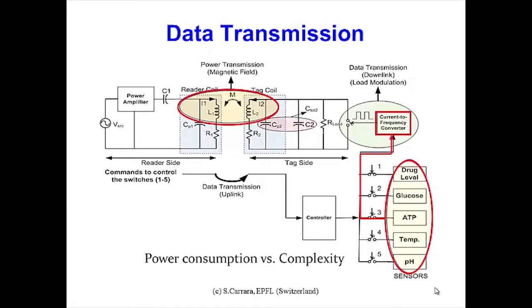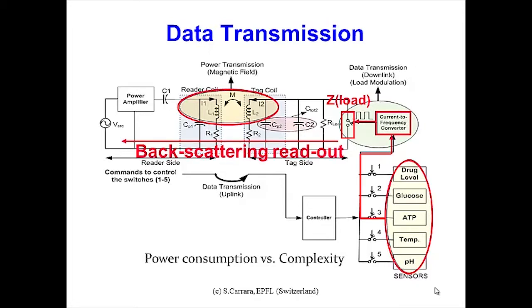transmission is very efficient if we have an impedance matching between the first and the second network in the system. If we are out of the best-match impedance condition, we are able to measure here this bad coupling between the first and the second network. So we can use the frequency out of our current-to-frequency converter to drive a switch and, on purpose, get the two networks out of matching. In that way, we obtain what is called in the literature the backscattering readout of our data. We will measure here a frequency of going in and out of the matching, which is related to the frequency of the converter, which is directly related to the current of our sensor. So we are measuring here a frequency which is directly related to the measurement of the sensor in our implant.